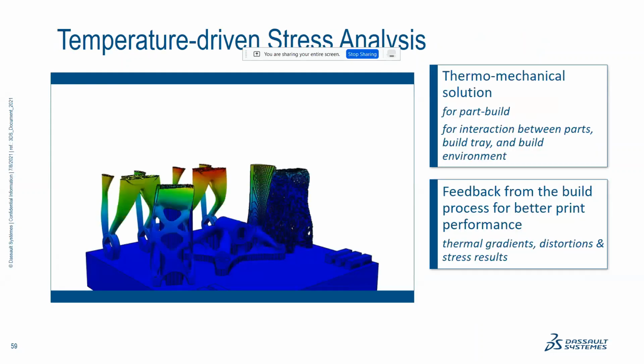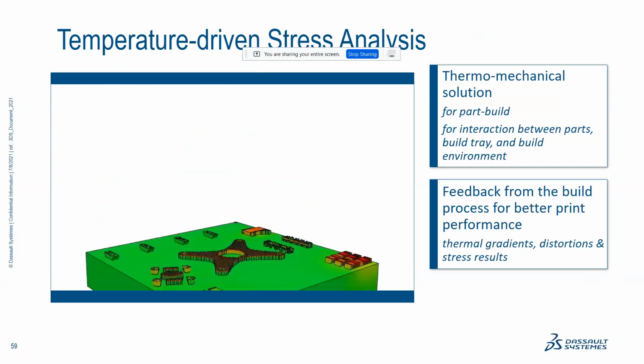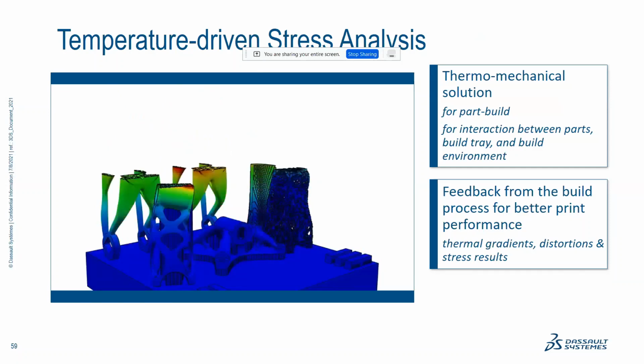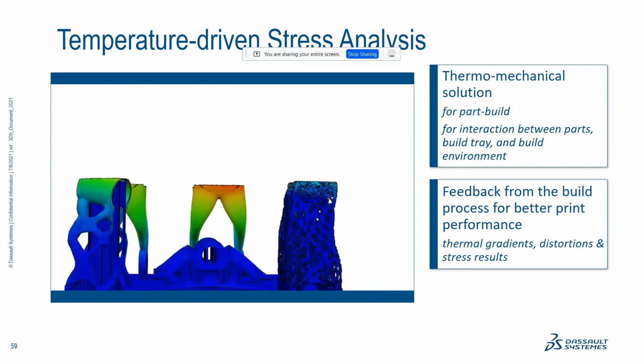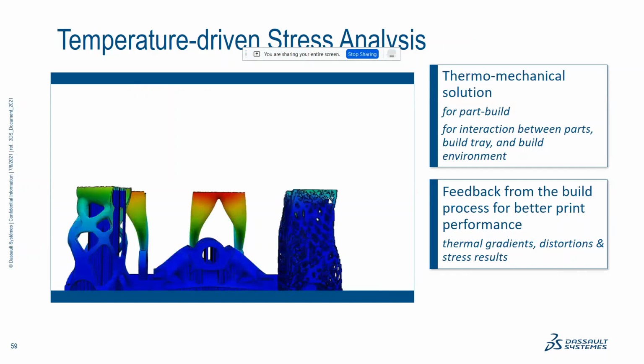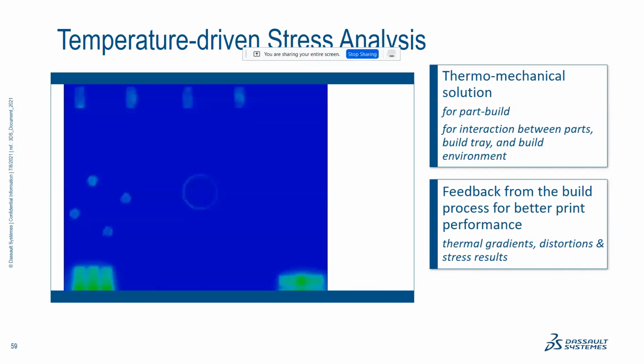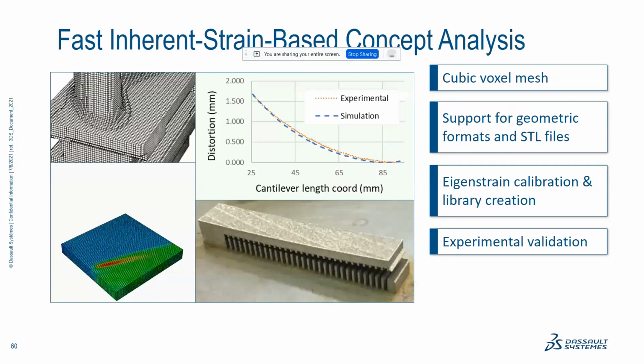So this kind of a thermomechanical solution framework gives a good feedback for the build performance. So as you can see, we can get the thermal gradients as well as the distortions and the stress result. So in this case, we are looking at a nested part print. So we talked about the fast inherent strain method. So what is the difference between this and that?